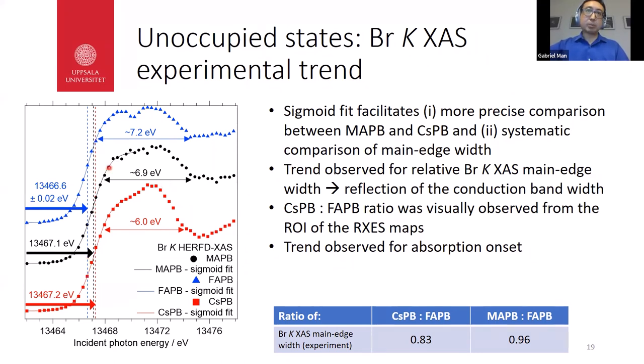I've chosen to use a sigmoid fit for a couple of reasons. One is that the absorption onset for black and red are pretty close together, and the sigmoid fit allows us to differentiate between the two, because the uncertainty in the fit is less than the difference. The second reason is that a sigmoid fit allows us to do a systematic comparison of the experimental main edge width. Here we're defining the width to be 75% of the step height.